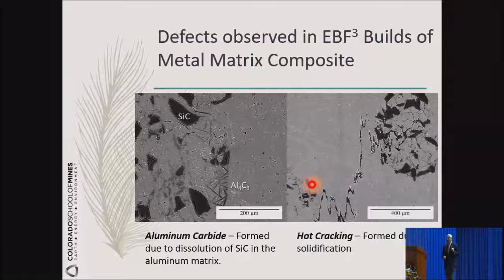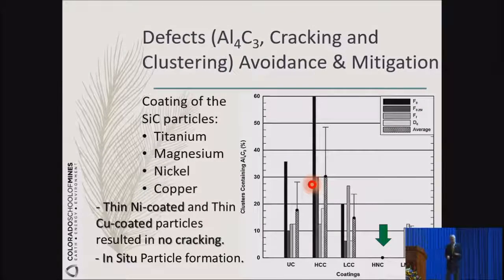So then we thought, okay, what we can do is coat each one of those fibers. So silicon carbide, you coat it. So here, if you look at it, we tried titanium coating, magnesium coating, nickel coating, copper coating. We learned a lot, is that too thick a coating does not work. You know why? Because with too thick a coating, that particulate will behave like a piece of metal. It won't behave like a ceramic particle. So thin coating is what works, okay? And so here, thin nickel coating and thin copper coated particles work better. It changes the distribution of the particle, allowing a little bit better dispersion. So there's a lot of modeling work that needs to be done in that part.